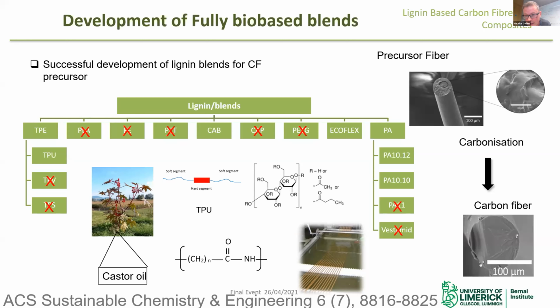The other materials that are not X'd out, these were compatible with lignin, and that means that when we mixed them, it was a homogeneous phase, and when we carbonize them, we got a nice carbon phase with no voids. And you can see an example of that here. So this is a precursor fiber up in the top right hand side, and this is a blend of lignin with thermoplastic polyurethane that has been derived from castor oil. And you can see the cross section using scanning electron microscope, and there's no voids in it. Then we carbonized that precursor fiber, and we produced a carbon fiber with no voids. So that was an excellent result. That was published in Sustainable Chemistry and Engineering not so long ago.